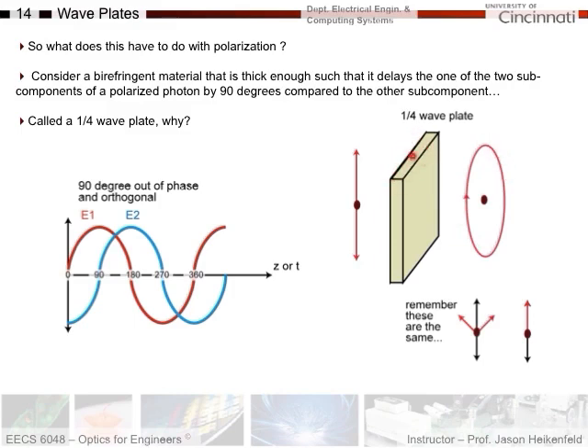Well, we know when we looked at this experiment that it goes from linear polarized light to circularly polarized light. This type of material, a birefringent material, is called a quarter wave plate. And what happens, again, is basically one of the polarizations, so let's break this up into the resultant vectors instead. So, we'll say it's coming in like this instead of this interpretation. This one would see an axis through the material like this. This one would see an axis through the material like this. And the key point is that the refractive index seen on this axis would be different than this one, and you can make this just by making this plastic by stretching all the molecules in this direction, as you make the plastic. And as a result, you get this phase delay because the axis that has a higher refractive index will be delayed. It travels slower. Remember, speed of light travels lower in a higher refractive index medium. And therefore, if you make the thickness of this correct, you can get a 90 degree phase delay, which is one quarter of 360 degrees, hence you call this a quarter wave plate, hence it turns linear polarized light into circularly polarized light.